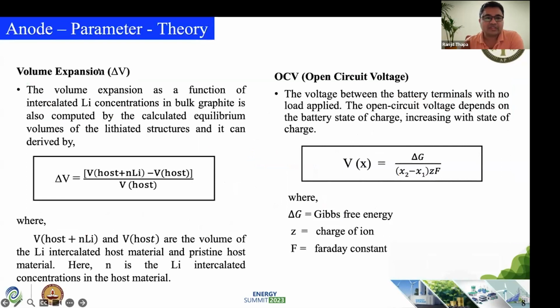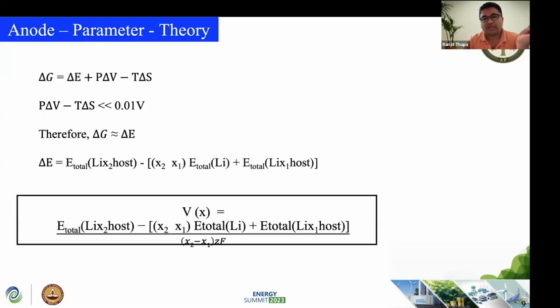So how to calculate volume expansion, I have just given for the student audience: you can easily calculate the volume expansion from the intercalation or de-intercalation process by calculating the volume, and we can easily find it out from our theoretical point of view. Open circuit voltage, which is very much equivalent to your potential, which I have shown in the previous slides, we can also calculate by finding the Gibbs free energy, the concentration of how many lithium we are taking out, and then the Faraday constant. By using this method, we can easily calculate the open circuit voltage. And another parameter is the formation energy, because how much lithium you are putting in or extracting, based on that, the stability of the material is defined by the formation energy, which we can calculate using this formula.